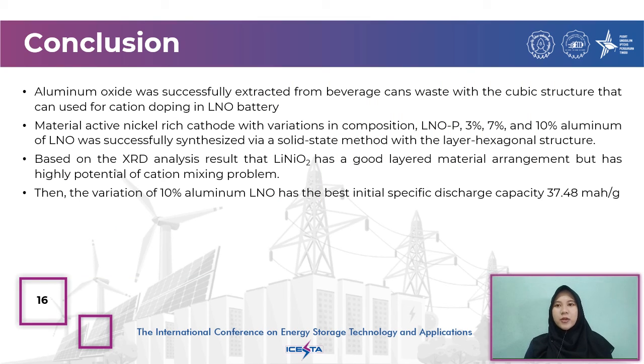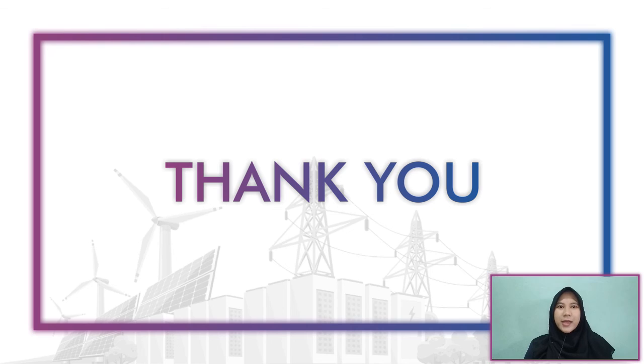From our research, we can conclude that aluminum oxide was successfully extracted from beverage can waste with a cubic structure that can be used for cation doping in LiNiO batteries. Nickel-rich cathode active material with variations of LiNiO pristine and 3%, 7%, and 10% alumina LiNiO was successfully synthesized via a solid-state method with a layered hexagonal structure. Based on XRD analysis, the LiNiO pristine has a good layer material arrangement but has a high potential for cation mixing problems. Then the 10% alumina LiNiO variation has the best initial specific discharge capacity, 37.48 mAh per gram.